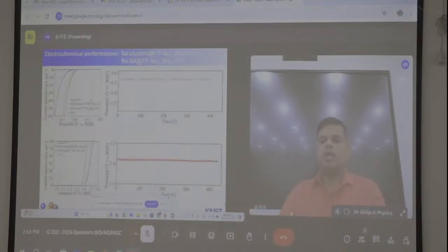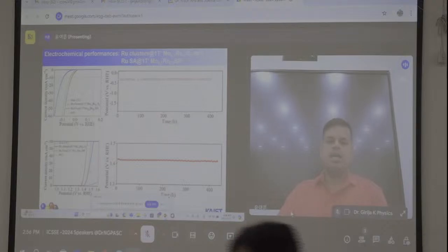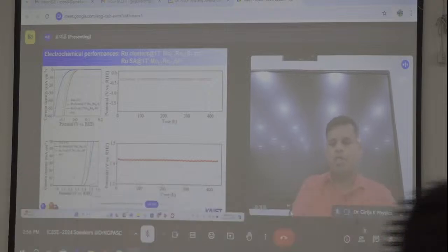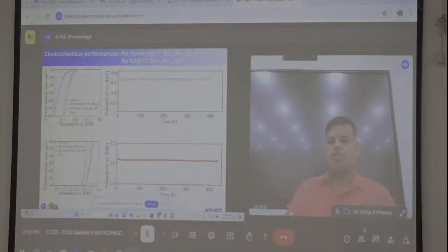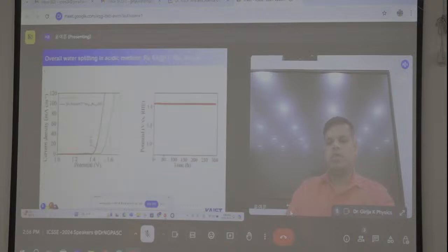So it may be another question. I also do the HER performance, where the blue one is cluster, and it may boost the performance. Even compared to platinum, it may give higher performance. And in case of the OER also, it may give a lower potential. So the durability for more than 400 hours may be stable in both HER and OER, and overall water splitting. The commercial one shows 1.53 volts, and the voltage is very low when compared to the previous materials.